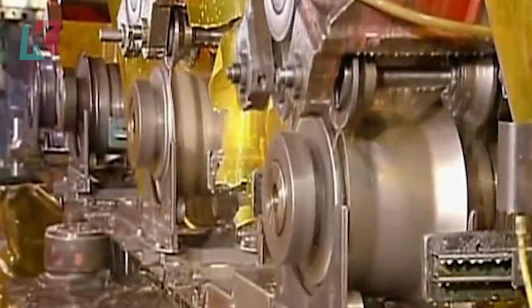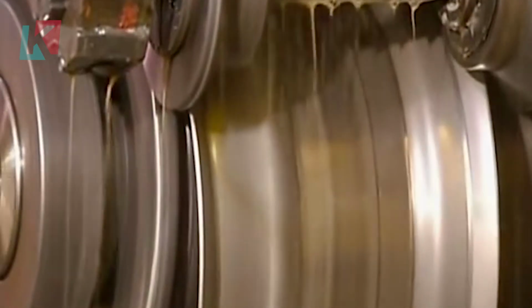The surface finishes achieved are remarkable. Bearing surfaces machined to 0.4 micrometers Ra, which is approaching mirror-like quality. These finishes aren't just for appearance. They reduce stress concentrations and improve fatigue life under racing conditions.